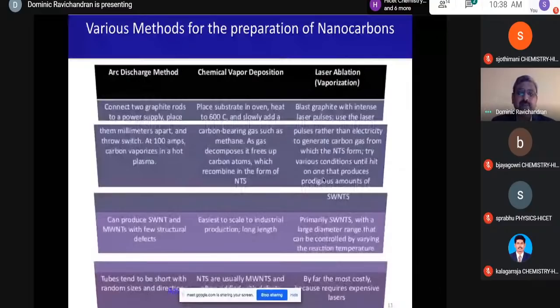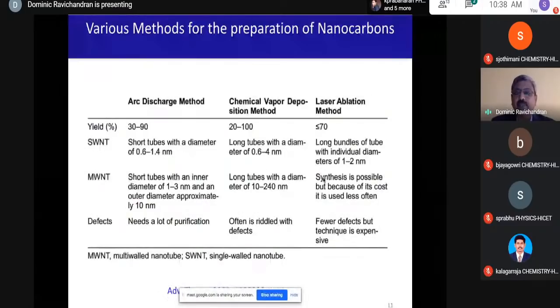Looking at the yield, the arc discharge method gives you a yield of 30 to 90%. In case of chemical vapor deposition, it's going to be 20 to 100%. And in case of laser ablation method, it is less than or equal to 70%.